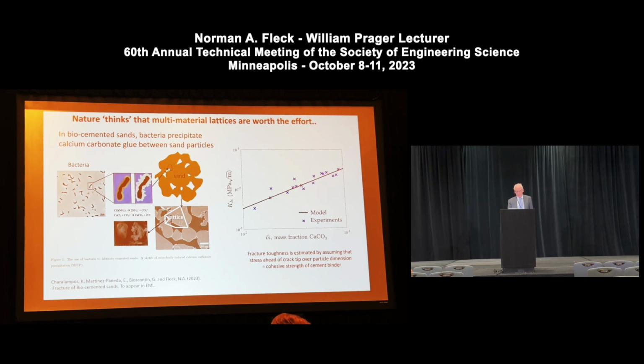Structurally, you can think of this porous aggregate behaving as a lattice. And one measures the fracture toughness, it scales with the mass fraction of the glue. And very simple modeling ideas, whether it's Ritchie Knott Rice or cohesive zone models, could be used to predict the effect of the amount of glue on the toughness.